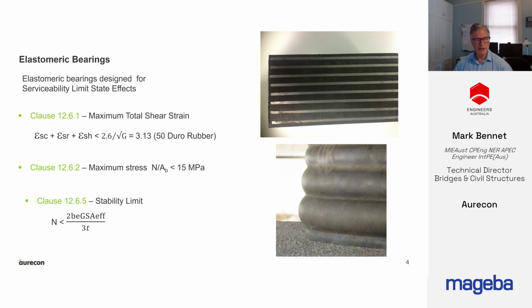The vertical load capacity is controlled by a number of criteria. The first is total shear strain, and you're actually calculating the strain in the rubber at the bulges between the steel plates. There's a general stress limit of 15 MPa, and there's a stability limit: bearings can undergo shear buckling as opposed to flexural buckling.